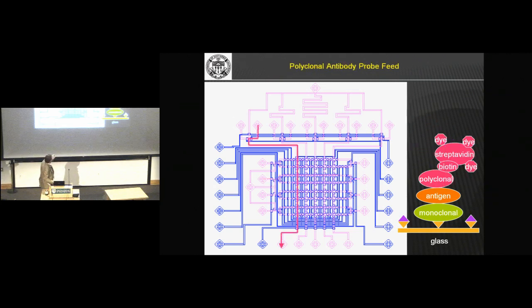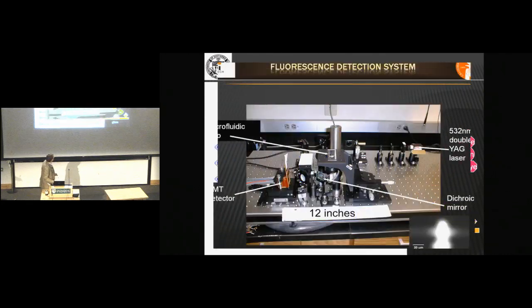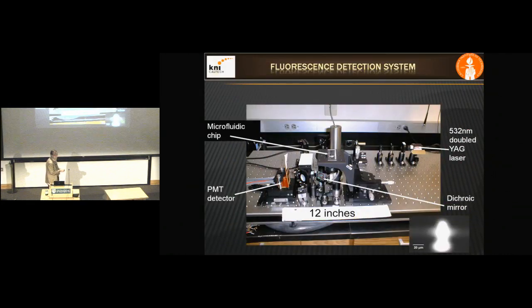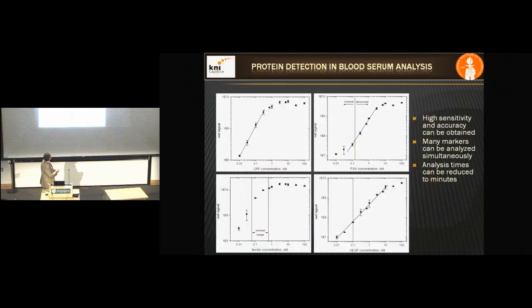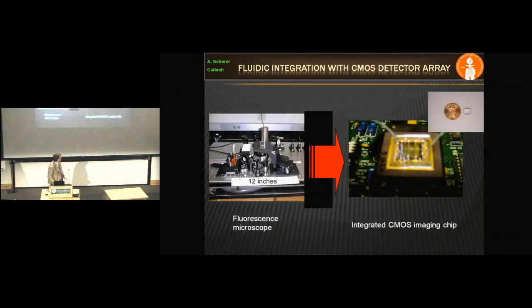And after that, I can finish the sandwich assay by putting a dye on top of it. And I can look at the fluorescence coming out of these intersections, and that tells me something about the concentration that I had. I can actually see a linear relationship between that fluorescence and the concentration, and I can measure things in a couple of tens of picomolar concentrations. Different proteins. VEGF is a cancer indicator. PSA is a prostate cancer indicator. CRP is C-reactive protein. It's a cardiovascular thing. So you can do many different things now, and you can make them in a very compact measurement system.